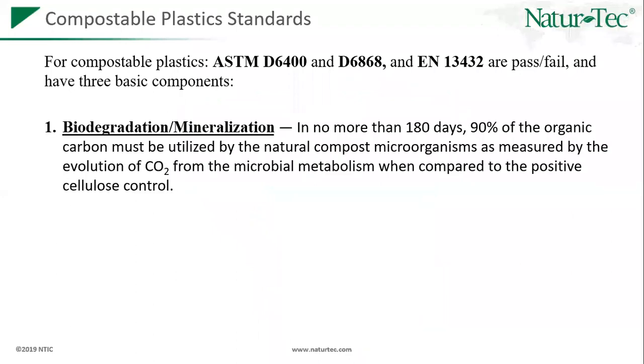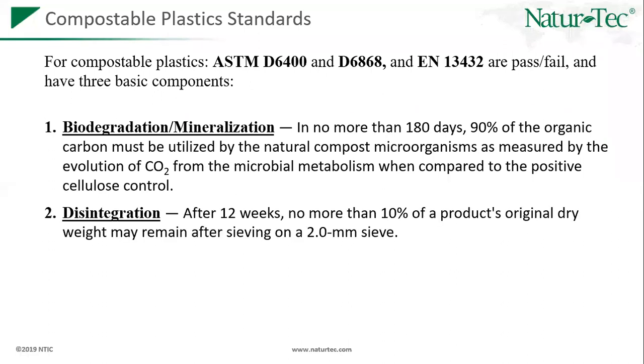The first one is called biodegradation or mineralization, which means in no more than 180 days, 90% of the organic carbon must be utilized by the microorganisms to form carbon dioxide when compared to a positive control of cellulose. This is the first stage in the standard. The second point in the standard is disintegration, which means after 12 weeks, no more than 10% of the product's original dry weight should remain after sieving on a 2 millimeter sieve.